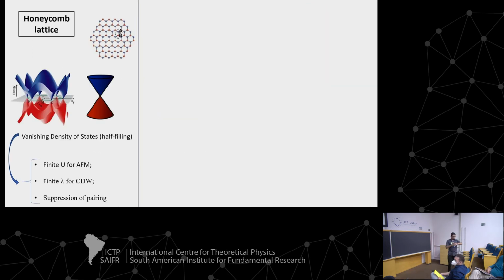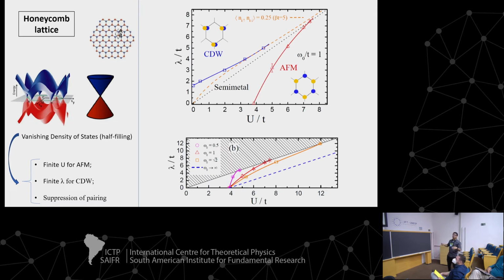Okay, we have repeated the same analysis to the honeycomb lattice, but the honeycomb lattice is completely different because we change the dispersion. We have Dirac fermions. And I will skip all of the details. I will show just the final result. This is the phase diagram in which in the middle part here, we don't have superconductivity. We have just a semi-metal, and this connects to your question, because if we increase more and more the value of lambda in U, we can have superconductivity, but I cannot access this part of the phase diagram because of the methodology that I used. But the most interesting thing here is that these critical lines, they are quite susceptible to the phonon frequencies. If I change the phonon frequencies here, for instance, from 0.5 to 1 to the square root of 2, the critical lines change a lot.